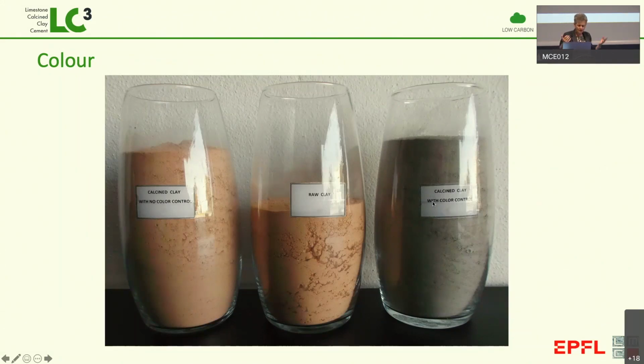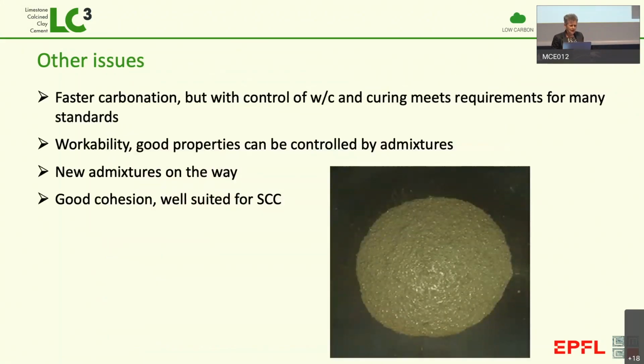People said, oh, calcined clays, they give you lots of problems of workability. It's very difficult to place them. Well, you can see here in this picture, you can produce very nice, easily flowing concrete also with calcined clays. And for these kind of placing applications, it can even have some advantages because the calcined clay avoids any problem of bleeding and segregation. You get very cohesive mixtures.